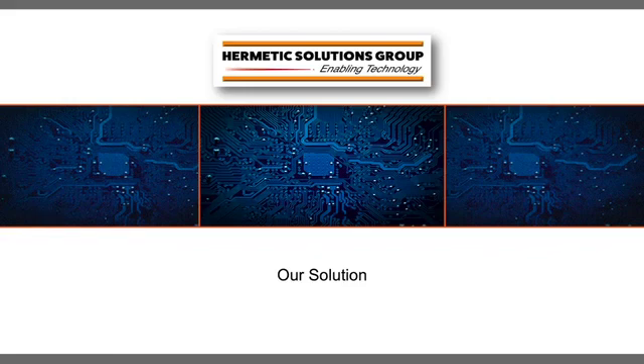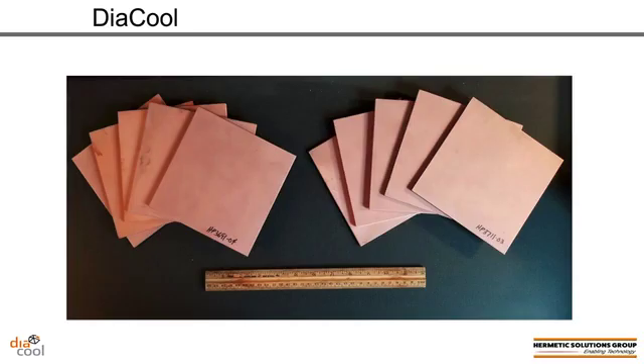So what's our solution? So this is our solution. This material that you're seeing in this image is our Diacool material. Diacool is a trademark name that represents metal matrix composites built using diamond in the matrix. Now, in this case, Diacool could mean copper diamond, as you see here, or aluminum diamond, or silver diamond. All fall under that Diacool trademark name. The material is made in large area sheets like you see here. In this case, these plates are all 150 millimeters square, or in English, roughly 6 inches square.